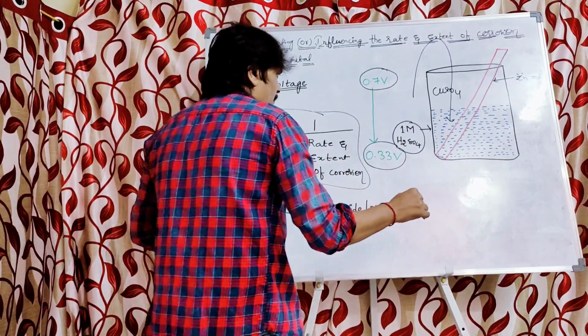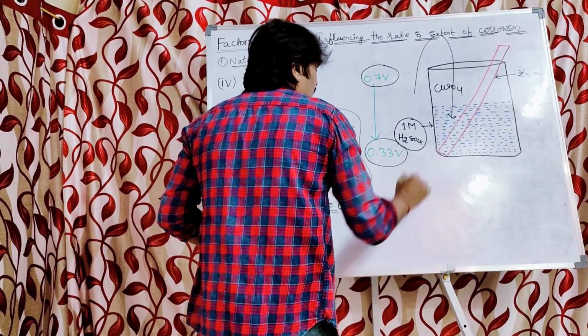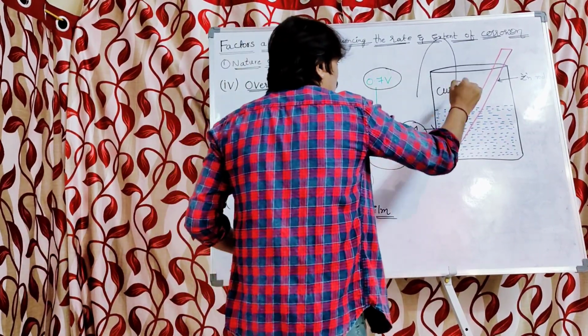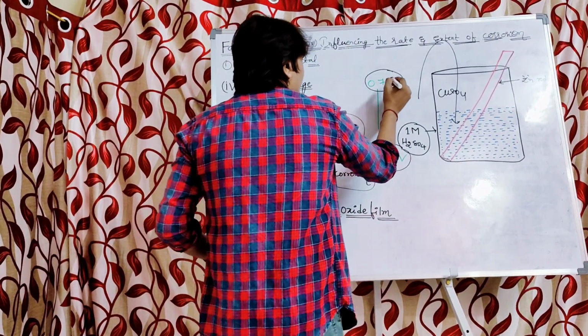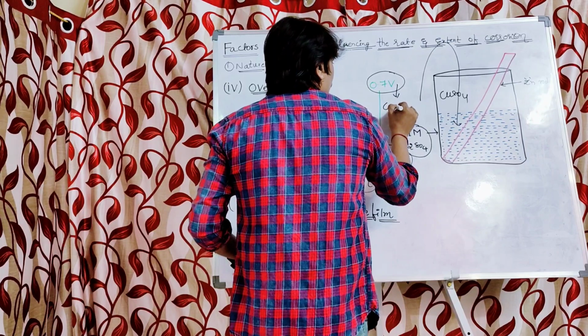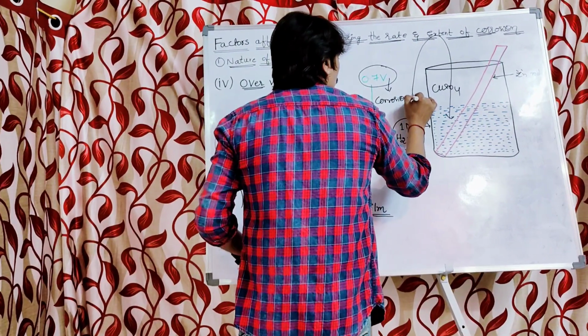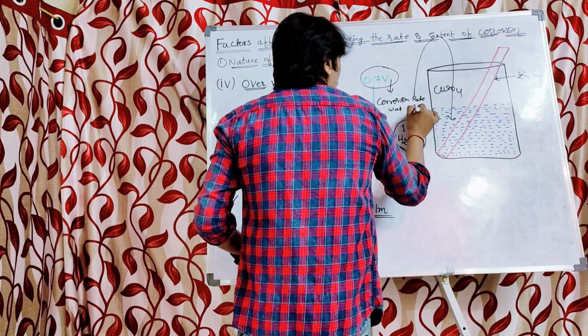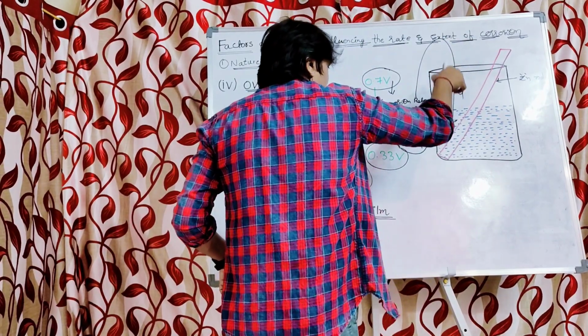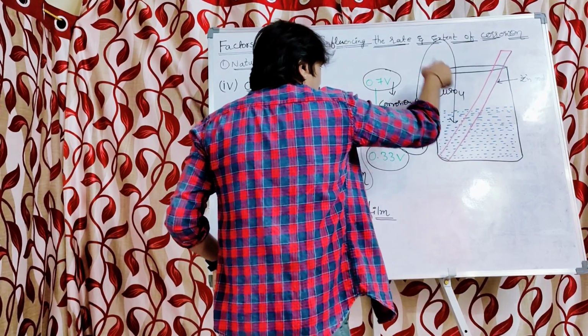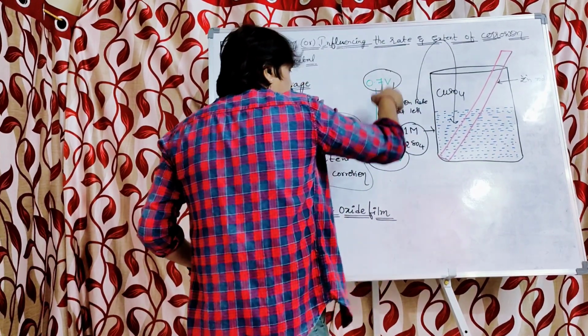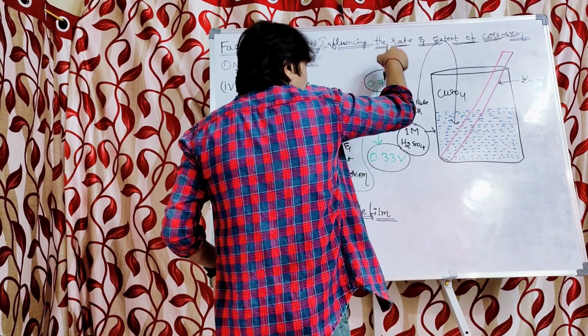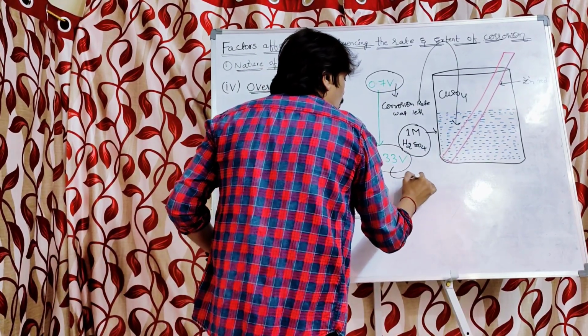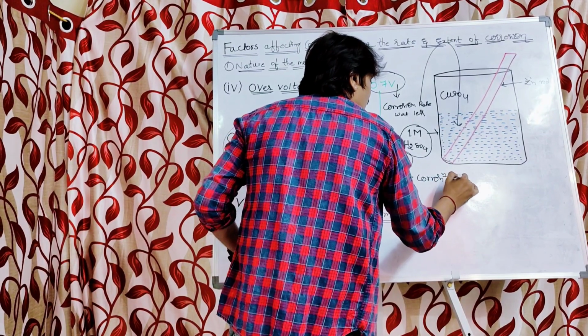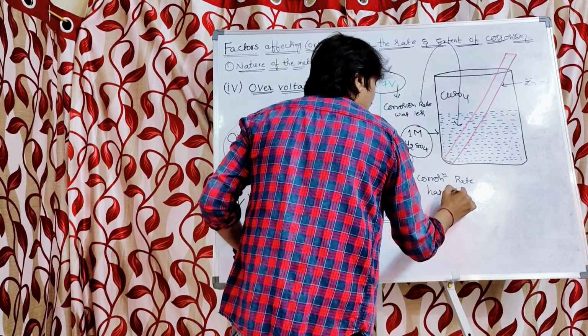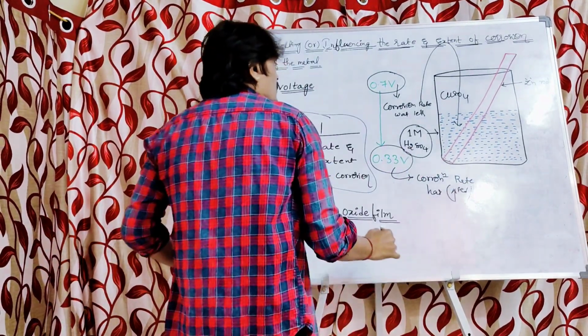Initially, when there was no copper sulfate, the overvoltage of the zinc rod was 0.7 volt. When it was 0.7 volt, the corrosion rate was less. But when they added the copper sulfate to the 1 molar sulfuric acid solution, the new condition developed, by which the overvoltage dropped from 0.7 volt to 0.33. When the overvoltage dropped, they observed that the corrosion rate increased.